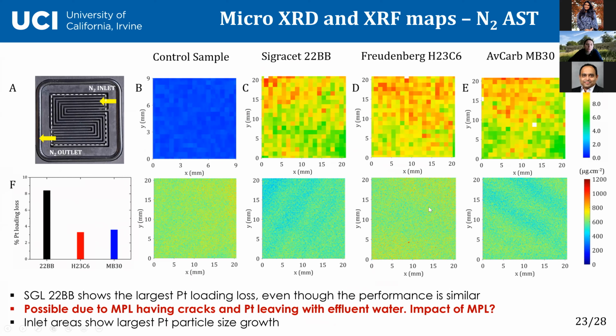This is a loading map showing that actually 22BB SGL loses more platinum than the others. And this is possibly due to SGL having microporous layer cracks. And you can think cracks help water removal from catalyst layer. So water will carry platinum and platinum will leave the system. So that's how we started to look into impact of microporous layer.